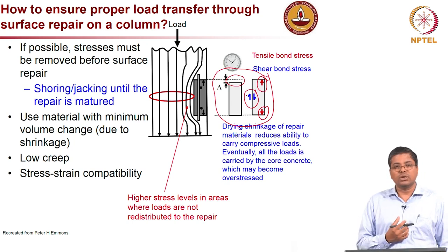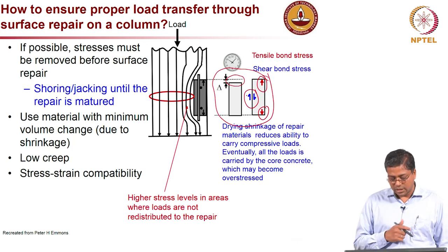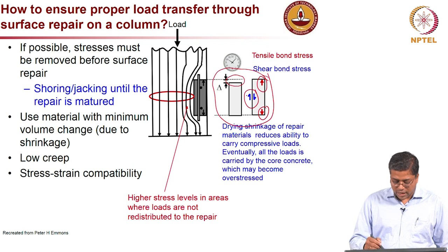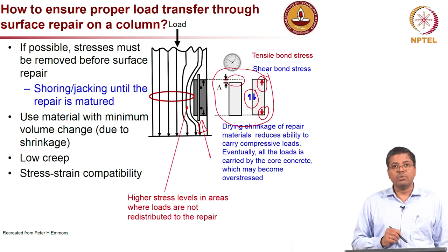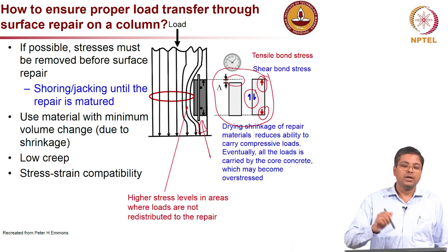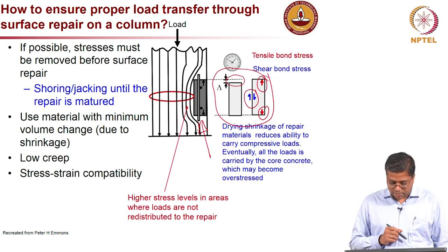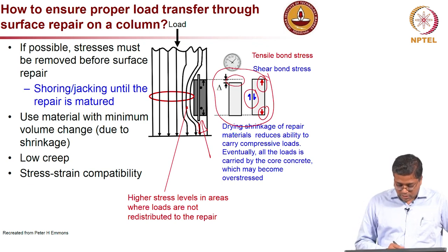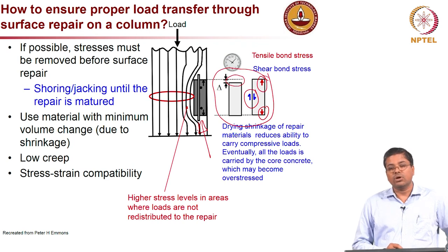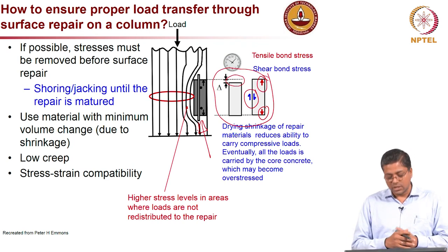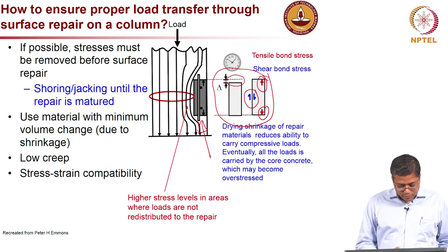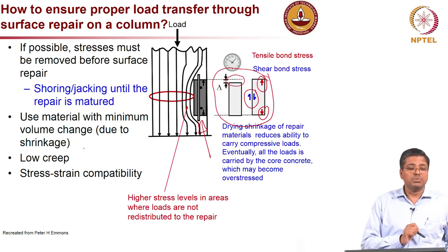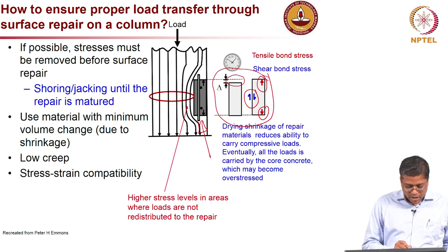And now how do we ensure that even if there is a dimensional variation, there is still stress transfer or load transfer? We can provide a rebar, as is shown here. We can provide a rebar which goes through the repair material and transfers the load to the substrate. Okay, so this is also something very, very important, especially when you are talking about structures which have significant loading, etc. So the selection of material becomes very crucial here. For the selection of repair material, you have to use a material with minimal volume change.